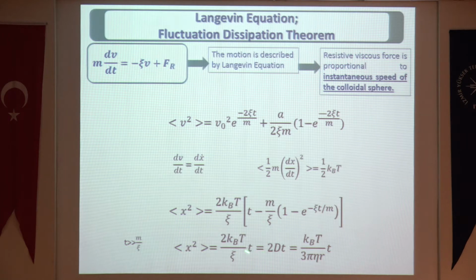So here, this viscosity, or excuse me, the frictional coefficient, we measured from this experiment, and we can end up getting its value. It is related to the diffusion coefficient, capital D, and this viscosity is also related through 2D equal to kT over 3 pi eta times r, where r is the radius of the particle.